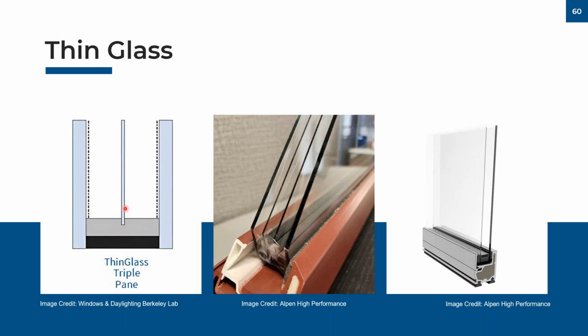So this thin glass can range from 2 millimeters thick all the way down to 0.5 millimeter thick. And so now we have the opportunity to add additional layers of low E coatings on these. And so this can be produced as a thin triple, or what you see in the center of your screen, or even a thin quad window.